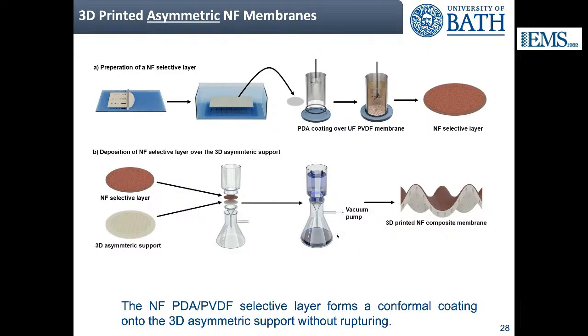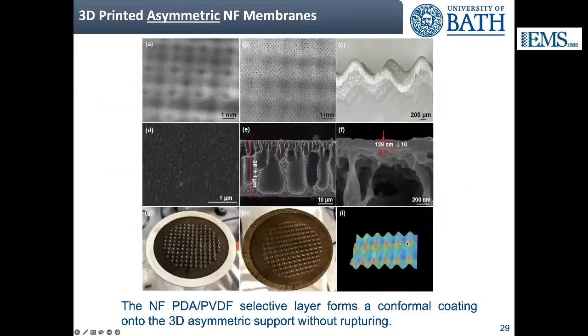So then what we did is we printed the object, this asymmetric support, and we then did a selective layer by coating polydopamine on PVDF. We then applied the selective layer onto the membrane, did vacuum suction, and it forms a very nice conformal coating onto the support. And this is the result you get.